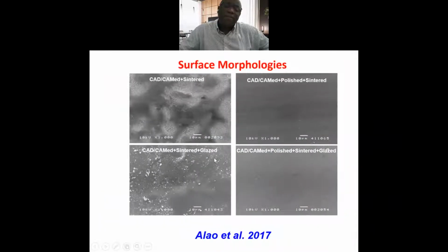Then also, glazing after the sintering leads to the formation of powdered debris. However, glazing after sintering does not significantly improve the surface roughness. That is the surface morphologies.